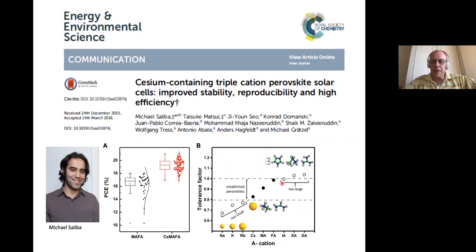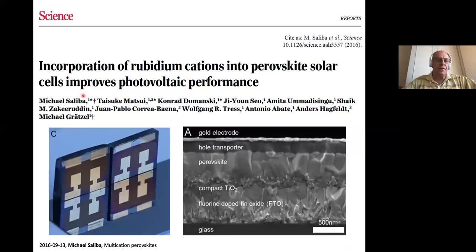So one thing we did then together with Michael Saliba was to try rubidium, to add as a quadruple, 4 cations. And that also gave very interesting stability data. You see here also the SEM pictures that you have very nice, almost columnar monolithic grains of the perovskite with not many grain boundaries, which is important in the horizontal direction. If you have grain boundaries like this, your charge, which goes up and down like this, has to cross them, so you don't want them. And with this more monolithic growth of the perovskite, you avoid such grain boundaries. We think that's one of the key aspects of this composition engineering.